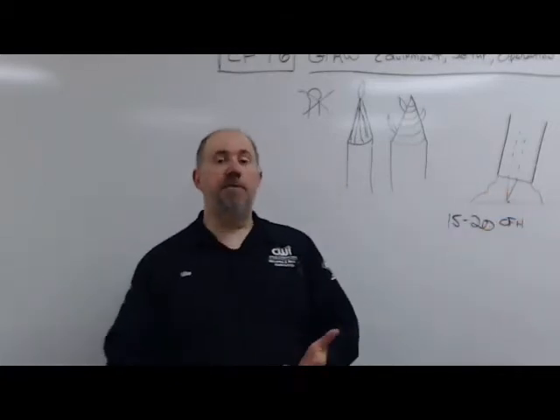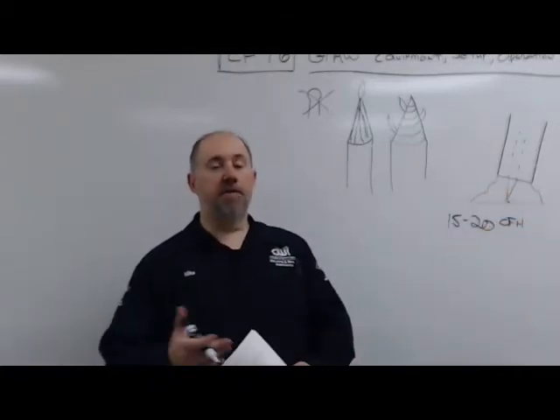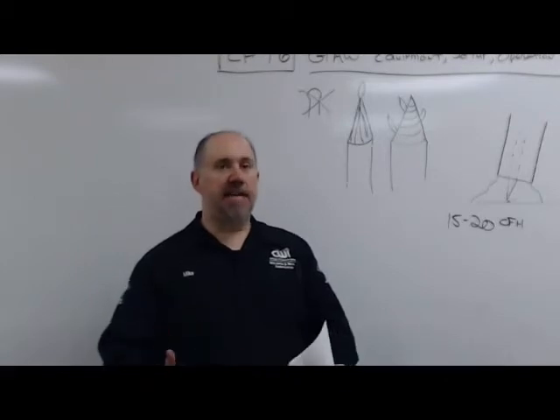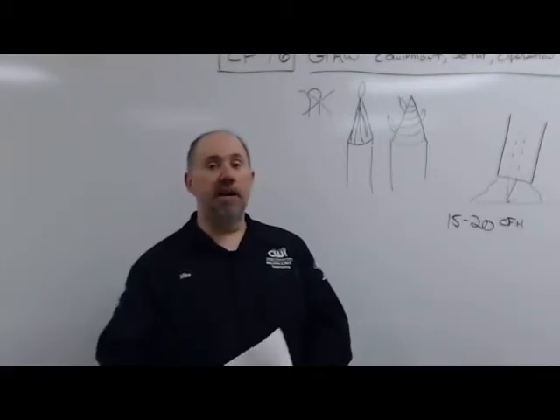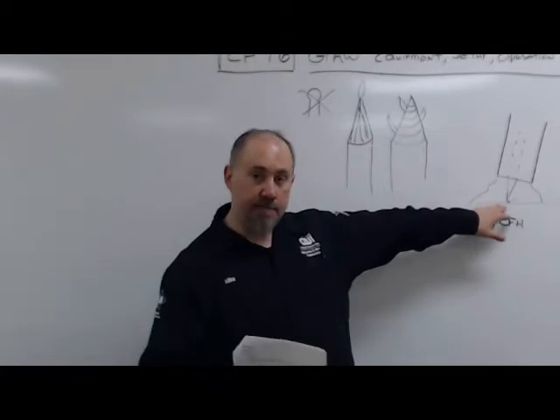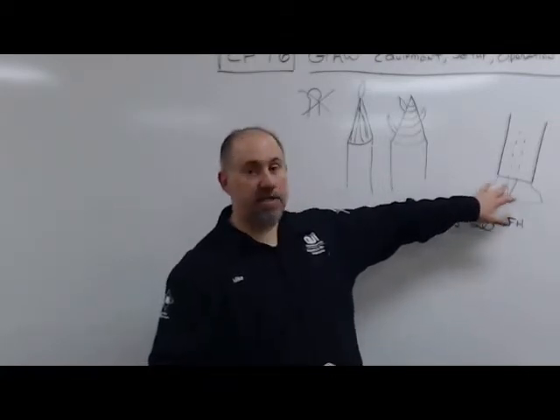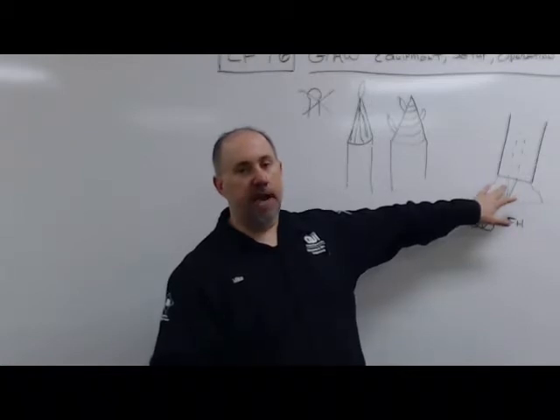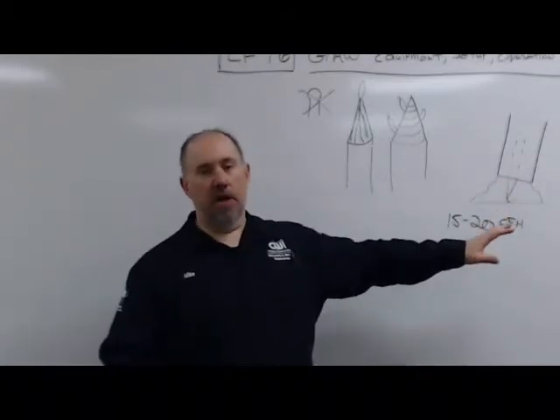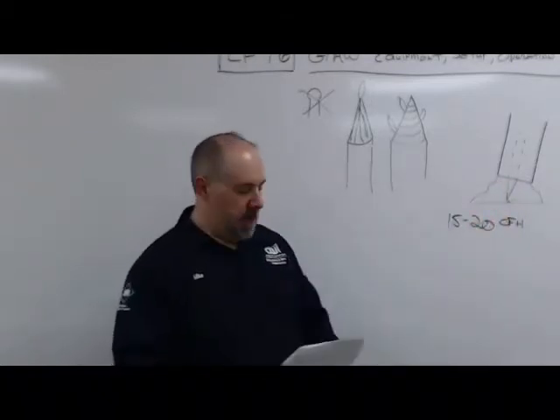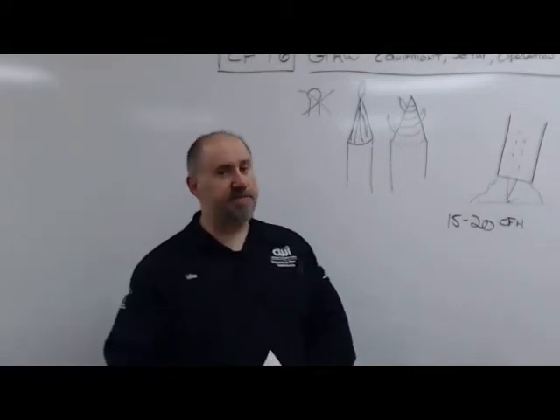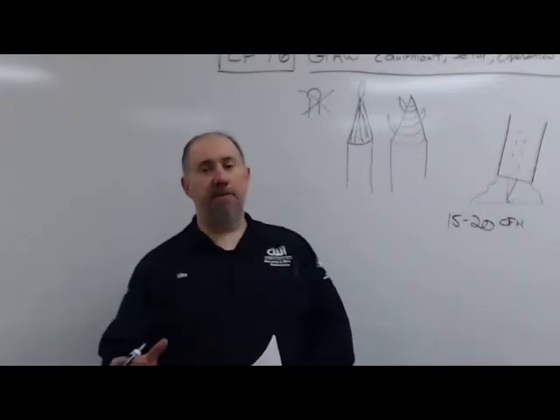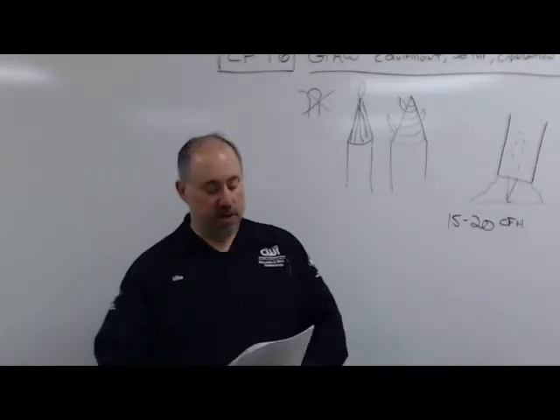And then after we're done welding, we have post-flow, which means it's going to flow gas for another 5, 6, 8, 10 seconds after we're done. And that is to protect the weld, it does that, but what it really does is it protects the tungsten while it's cooling down past its critical state. Post-flow is very, very important. Some materials, stainless steel is very important to shield that puddle after you're done, but we're also shielding the tungsten.